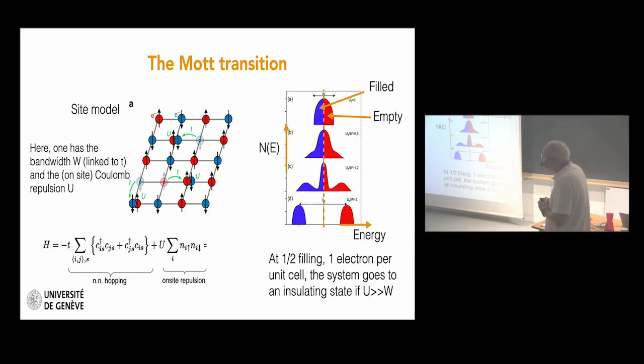So this is now a single-band model. In 2D, we have 1 electron per site. And one has to consider the bandwidth of the system, which is linked to the hopping, and the on-site Coulomb repulsion U, the price you pay to have 2 electrons on the same site. And I think you saw this already yesterday or on Tuesday. If you trace here the density of states as a function of energy, if the on-site repulsion is very small, you have the classical band picture. You have a half-filled band. The system is metallic. But if you switch on the interaction, or if you reduce the bandwidth, at some point your system is turning into a Mott insulator with this Mott gap that you see here.